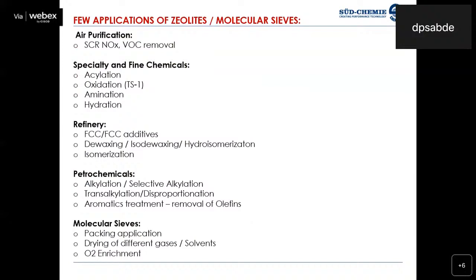This is used for 4 to 5 commercial applications for oxidation. That is phenol to catechol. You have cyclohexanone to cyclohexanone oxime. I mean to say epoxidation of propylene to propylene oxide, allyl chloride to epichlorohydrin. All these are basically commercial applications wherein the major contribution in this TS1 comes from the silica, and a suitable silica is used so as to ensure there is no contribution of the aluminum or the soda associated with that.